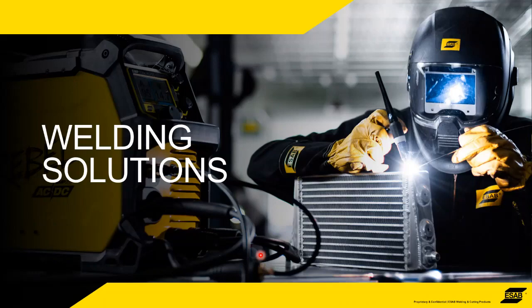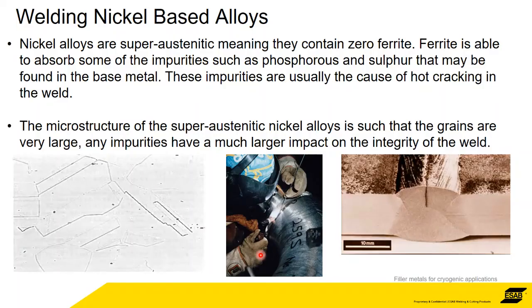So in terms of welding solution, the little tips and tricks, what needs to be taken into consideration with nickel-based alloys is that they are usually very, very low in ferrite or even zero ferrite. And what ferrite does in there, if you remember, we call them austenitic stainless steels, like a 304L or a 316L. We call them austenitics, but they're not super austenitic. They're austenitic, meaning that they do contain some ferrite. The nickel alloys are in the super austenitic region, which means they have very little ferrite.